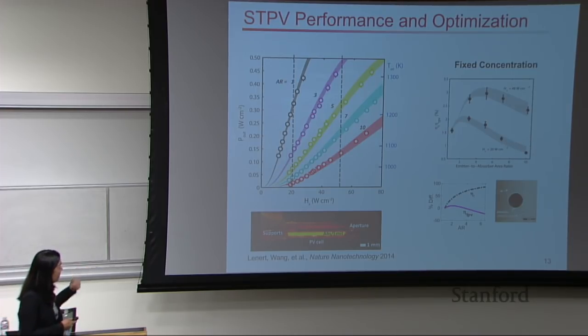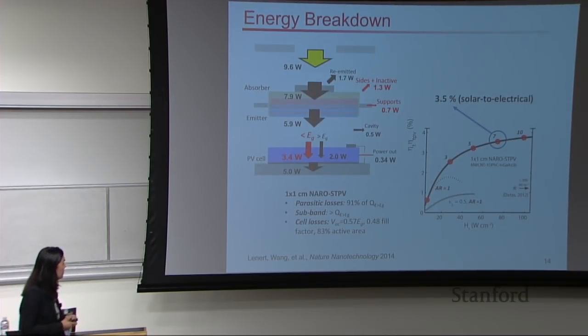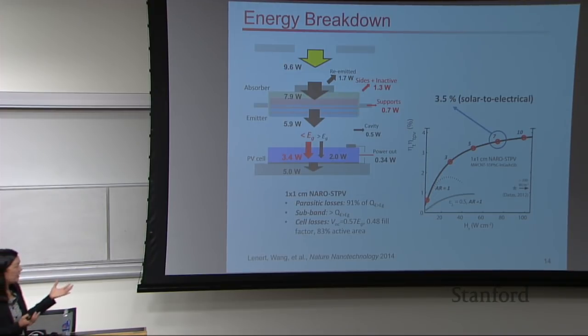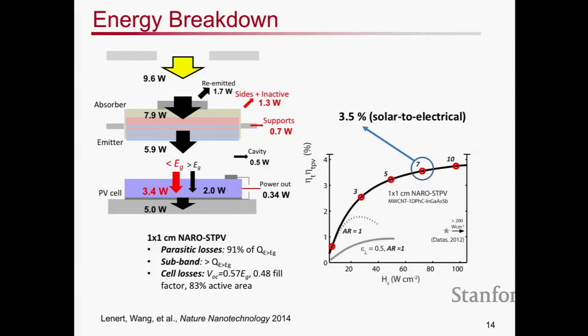With this understanding, we've been able to demonstrate with this platform about 3.5% solar to electrical energy conversion. Certainly that's still much lower than the theoretical limit, but also about 3x higher than what's been demonstrated previously. And we looked at specifically, where are we losing this energy in this conversion process?